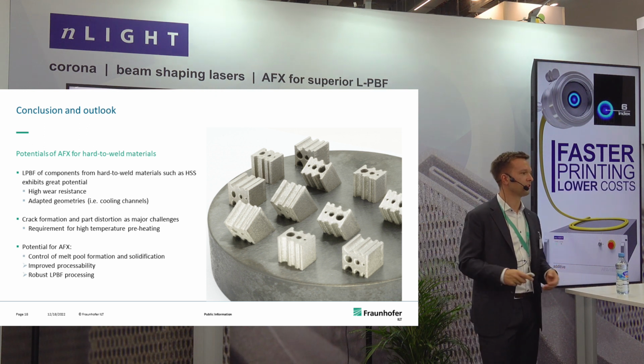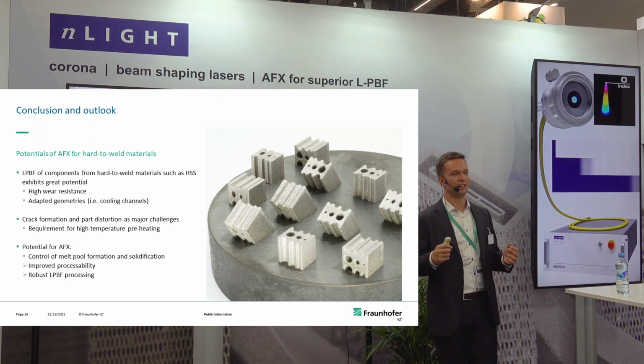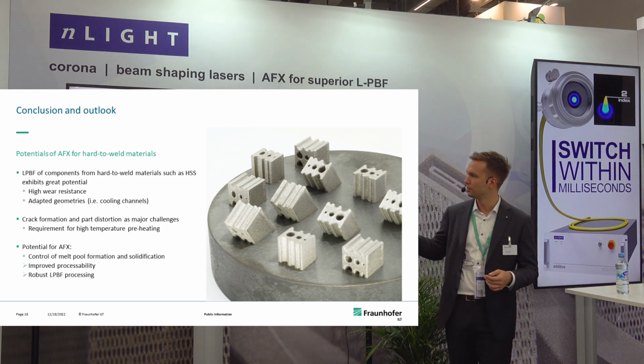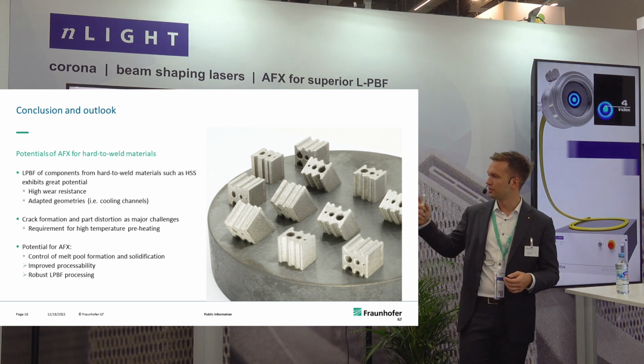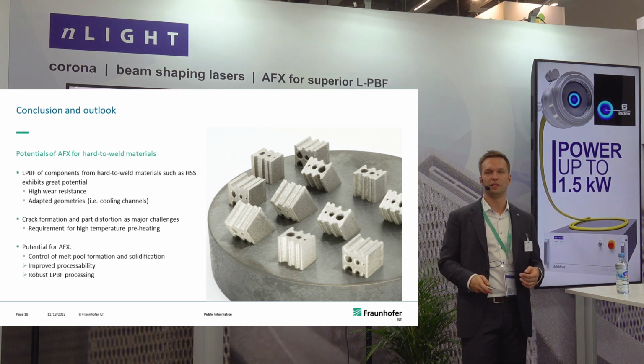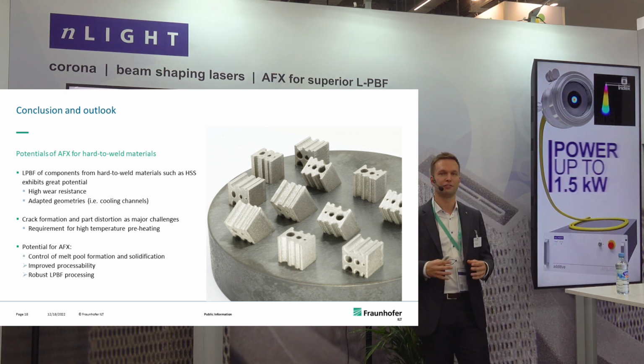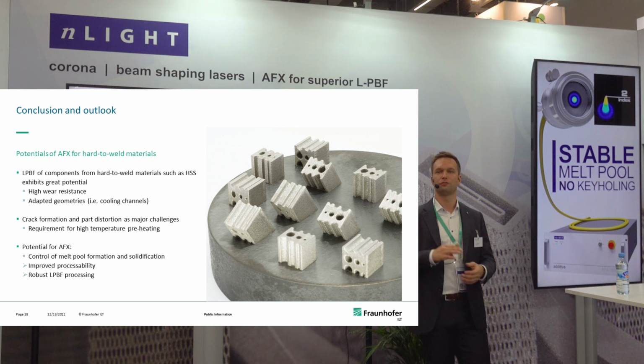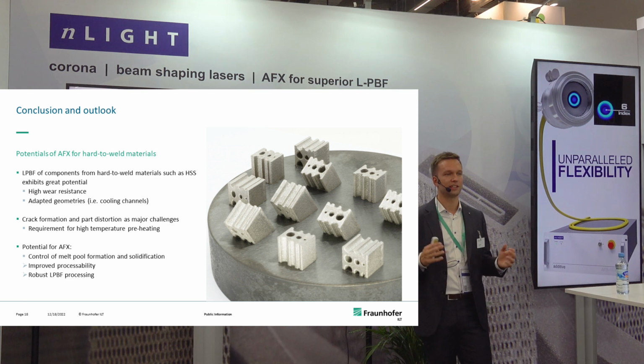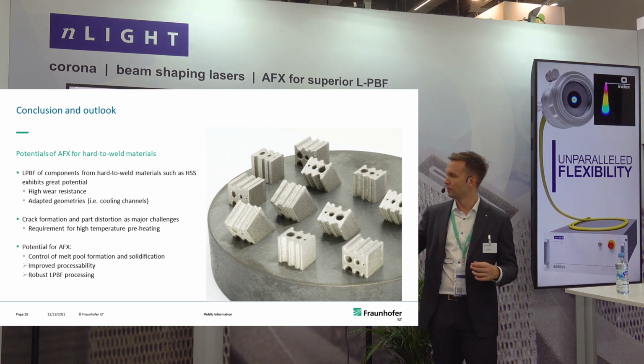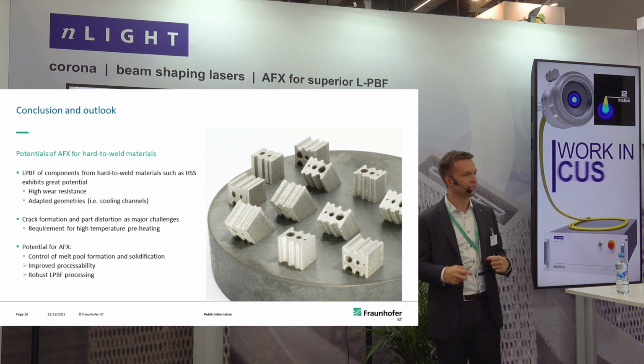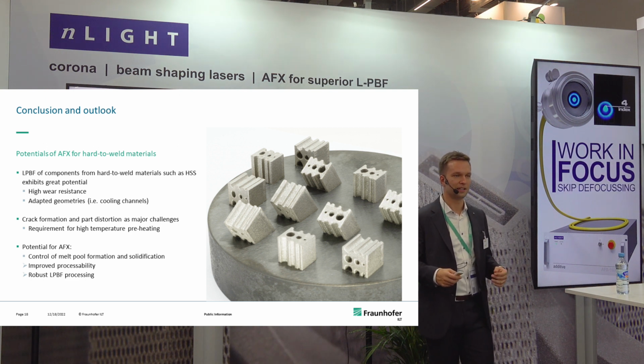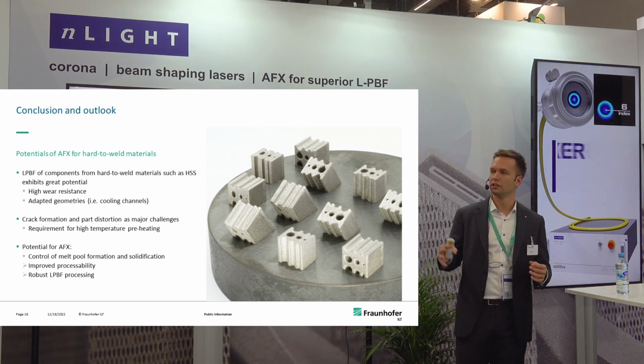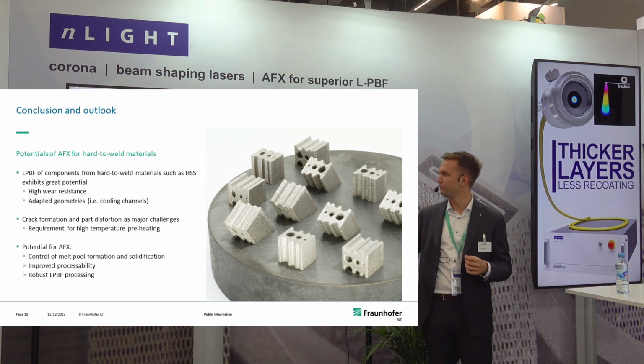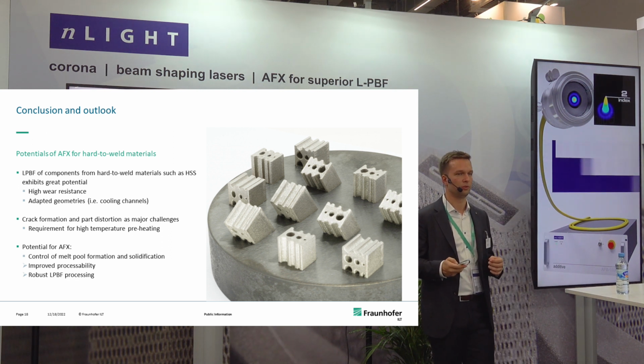But of course the cracking is a major challenge when it comes to manufacturing components out of these materials, and the potential for AFX we see at the moment is obviously that we have additional degrees of freedom apart from preheating to very high temperatures or modifying just our laser power, scan speed and hatch distance accordingly. We also have the control of our intensity distribution, which then helps us to control the solidification conditions and therefore reduce cracking in these components.